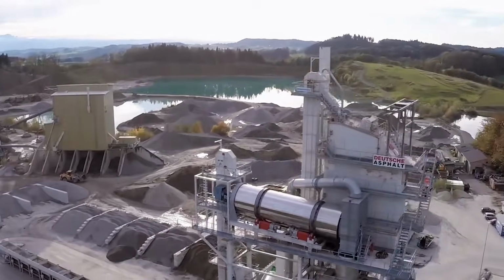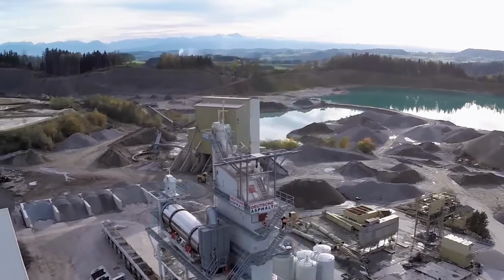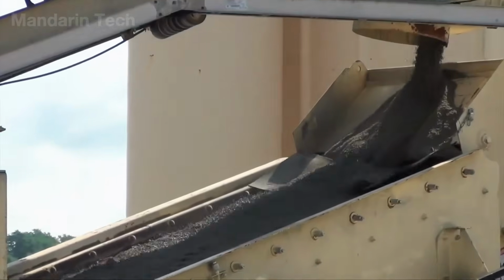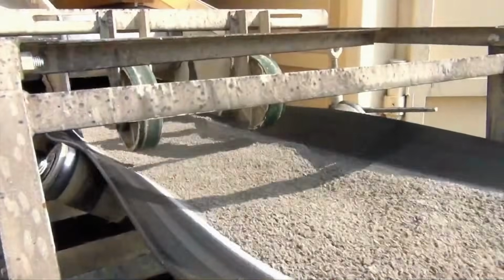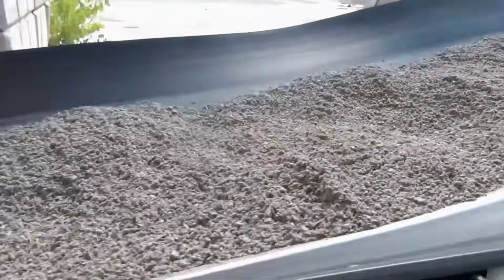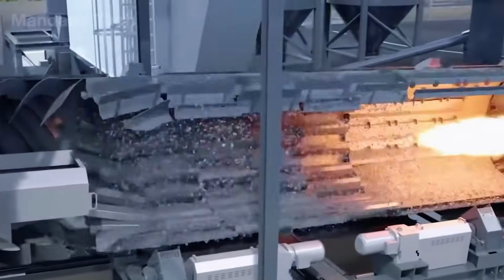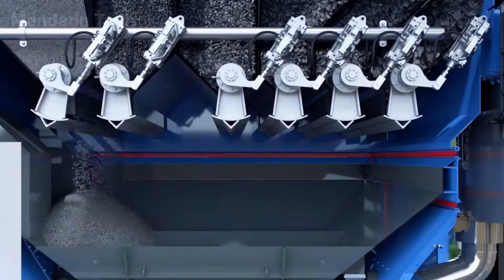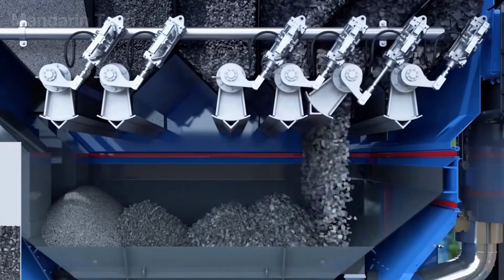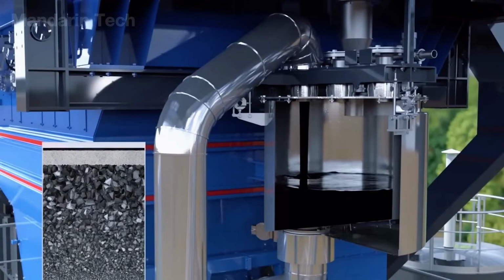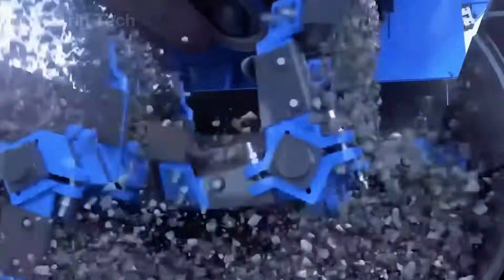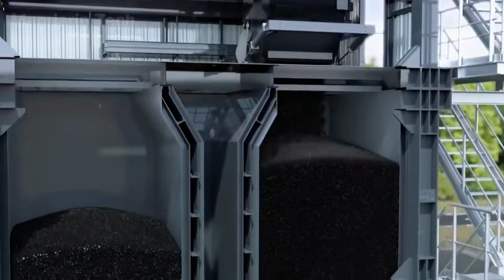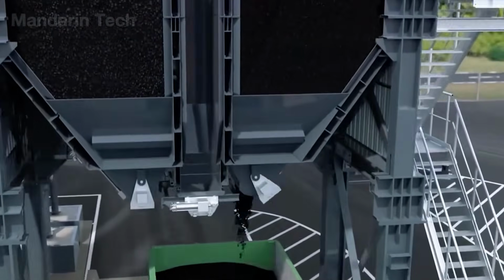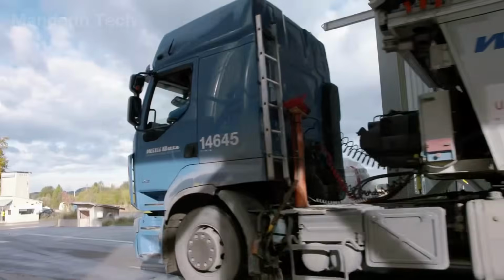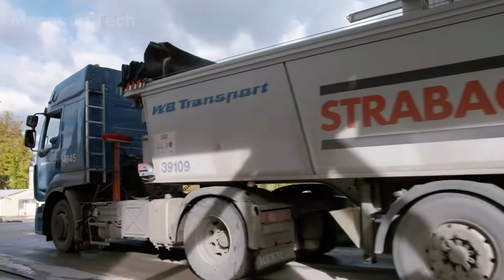newly produced material. Once the RAP has been sorted, it's mixed together with new asphalt binder, fresh aggregates, and a rejuvenator. This additive helps restore the elasticity of the old binder that has oxidized over time. At the mixing plant, the RAP is gradually heated to avoid burning the aged asphalt, then combined with hot binder and aggregates according to a pre-calculated formula. Some modern asphalt plants can use 30–60% RAP, while still producing a mix that performs just as well as brand new asphalt. This step is crucial because it saves natural resources, reduces CO2 emissions, and lowers overall construction costs.